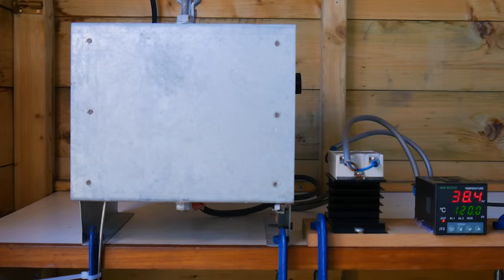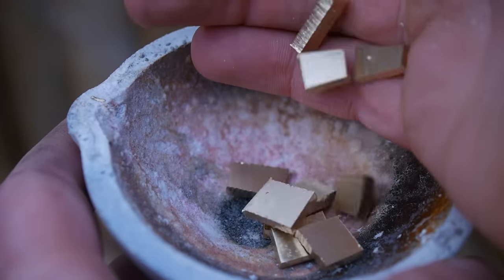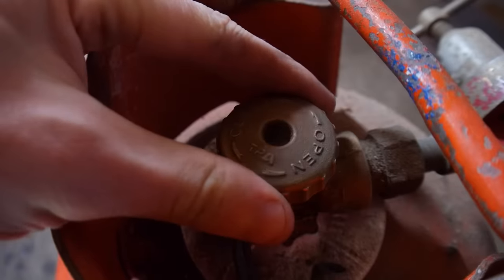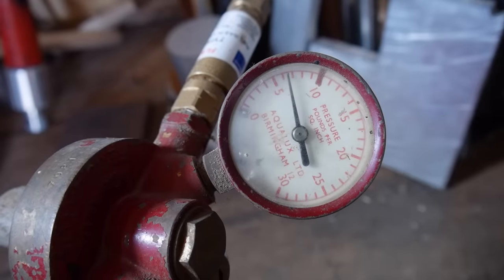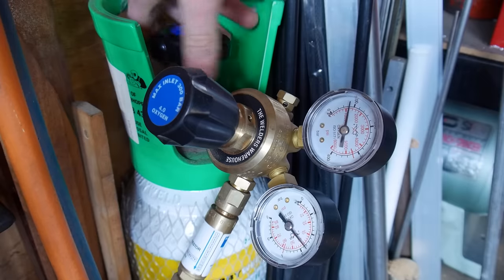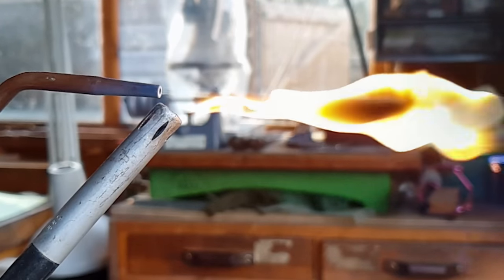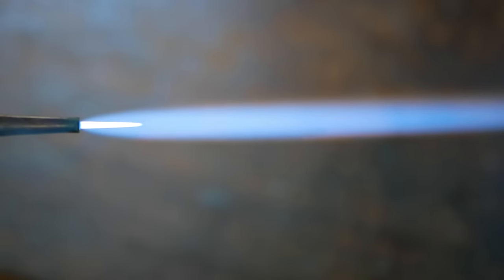I place the flask in the furnace and ramp the furnace to a starting temperature of 120 degrees centigrade. What follows is a series of temperature ramps up to 730 degrees centigrade which melts the wax and then burns off any residue and fully cures the investment mixture.